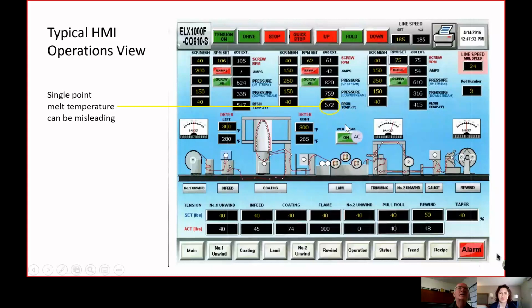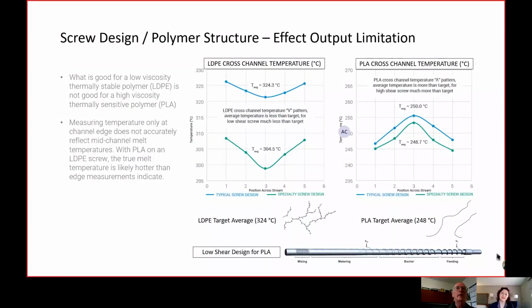I threw this slide in because I wanted to just talk about this melt temperature. So this is our HMI screen from our lab machine. And we're all used to looking at a single point melt temperature on our control screen. And this can be a little misleading, especially when we're looking at materials that don't run like our conventional materials. So during our trial, we put an adjustable thermocouple across the pipe. If you think of the flow coming down through a pipe, we were able to measure from the wall of the pipe to the center and across to the wall of the pipe again.